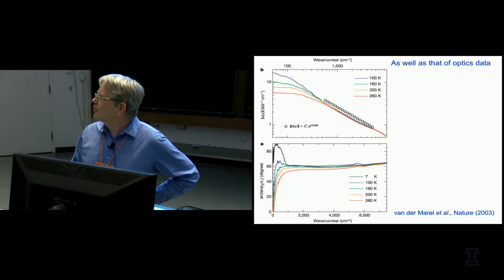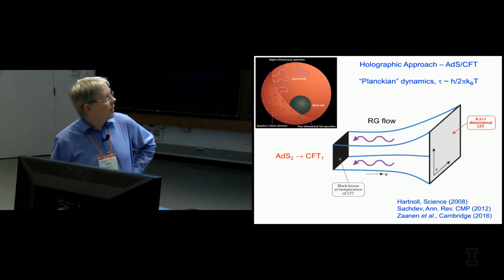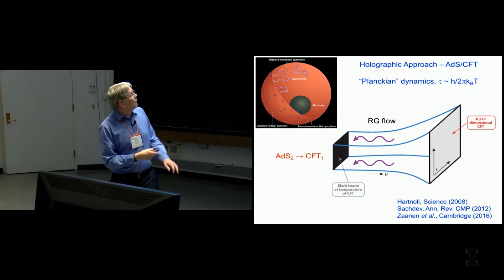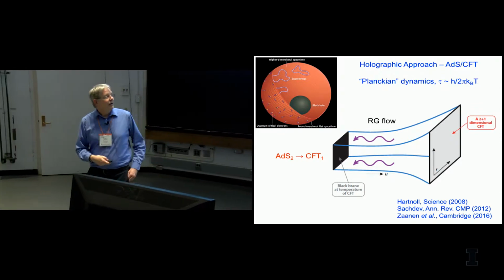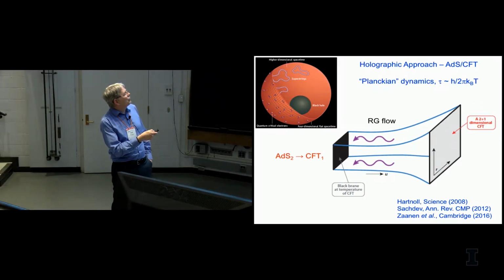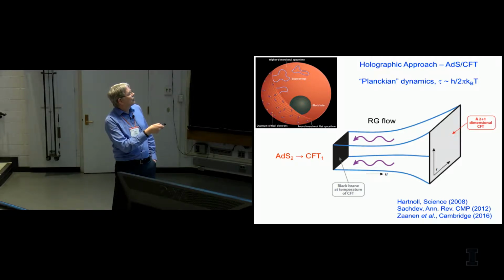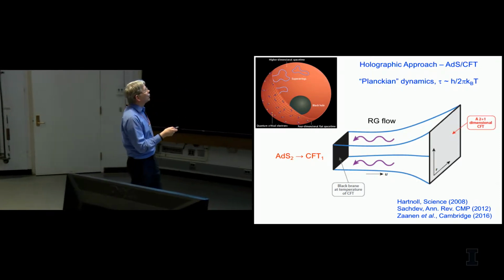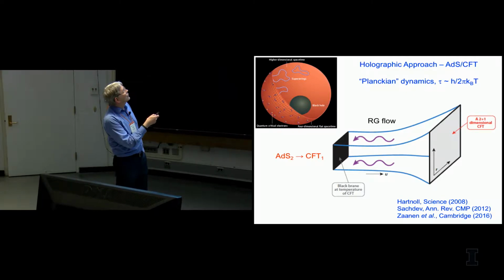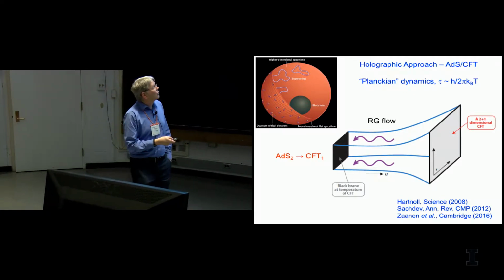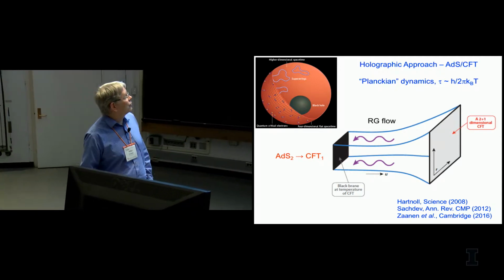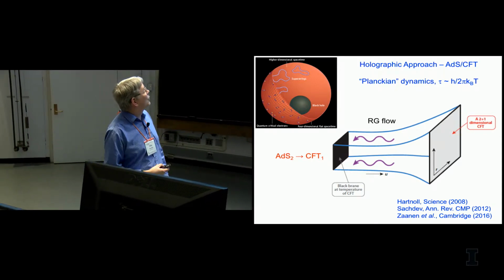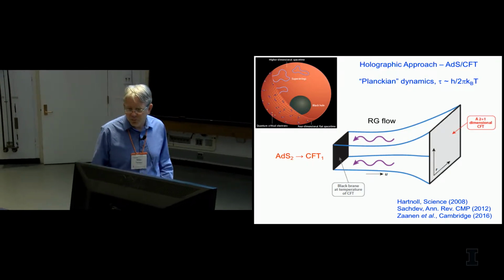And I don't want to dwell on this, but because Philip was one of the organizers, I had to sneak this in, that in fact there's this theory based on black holes in an AdS space, anti-de Sitter space, where basically you have some sort of a conformal field theory sitting on the boundary of the space-time, and as you go towards this black brane, which is the horizon of a black hole sitting in this AdS space, this dimension actually plays the role of a renormalization group flow. And based on these ideas, you get this concept of Planckian dynamics where the scattering rate goes like h over 2 pi kT, which is more or less consistent with data that you see in the cuprates. And so this is the idea that this strange metal phase can be represented by black hole physics.